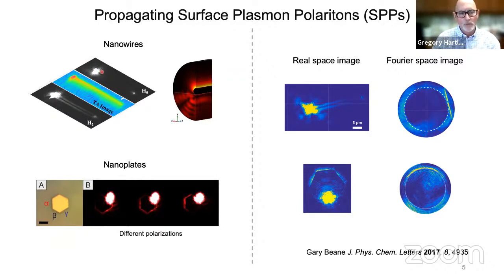So there are two modes. There's one mode that moves along the top of the wire at the metal-air interface, and there's another mode that moves along the bottom at the metal-glass interface, and they have different wave vectors, different momentum characteristics. The one that moves at the metal-glass interface has a fairly large wave vector, and so it can't couple to photons in the substrate.